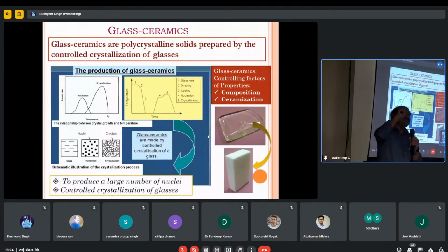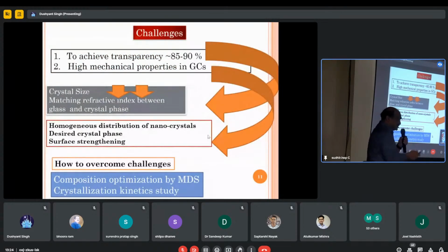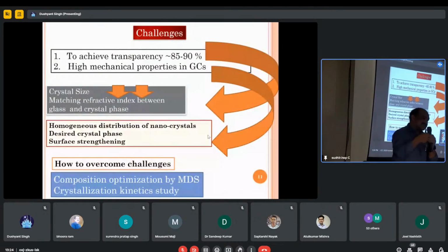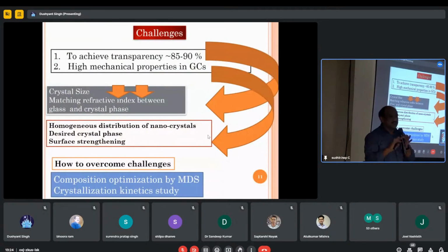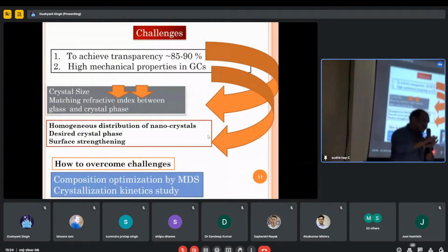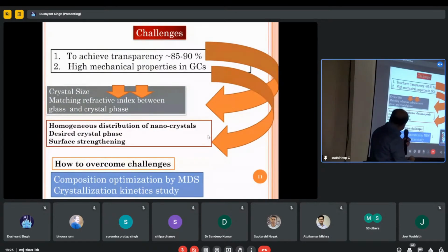Depending on the size of your crystals, it can be opaque, translucent, or transparent. If you can control the crystal size at the nanometer scale, then you can make transparent glass ceramics, which is much stronger than the glasses. I will show you some examples. So there are some challenges. When you induce crystals in the glass matrix, the transparency is going to be lost. So you have to control the crystal size precisely at the nanometer scale so that transparency is retained and it is useful for display applications. And mechanical properties you also have to maintain very high.